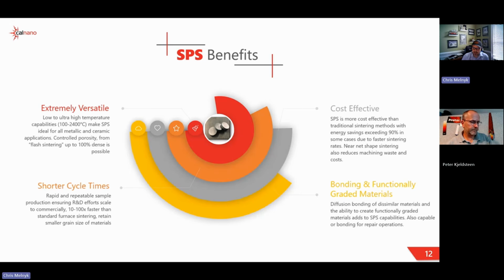especially for our European listeners, energy is of more importance, and it is also in America, and in the rest of North and South America as well. But yes, our friends at Idaho National Laboratory, Dr. Jorgen Ruffner over there, they did a nice little study where they found energy savings of 91% of total energy spent making a high temperature ceramic. I believe it was silicon carbide, don't quote me on that, but something in the 2000 degrees Celsius range for pressing, and they found a total energy savings of about 91%.